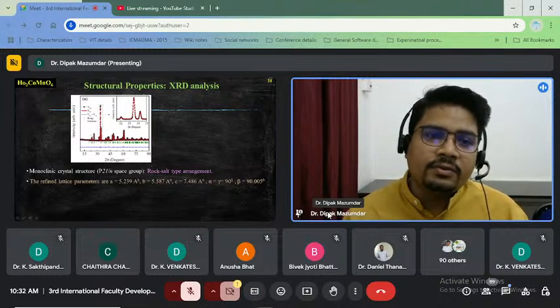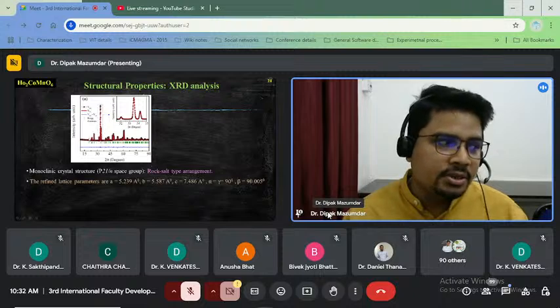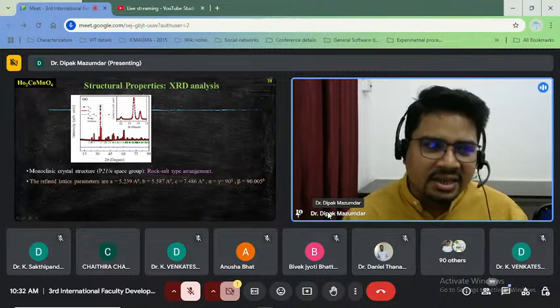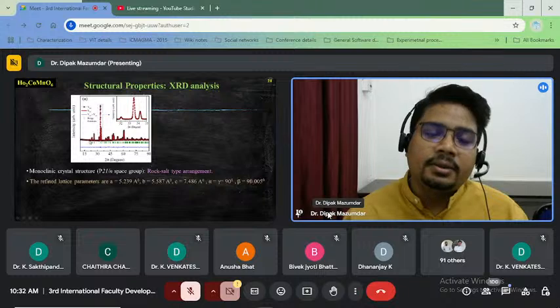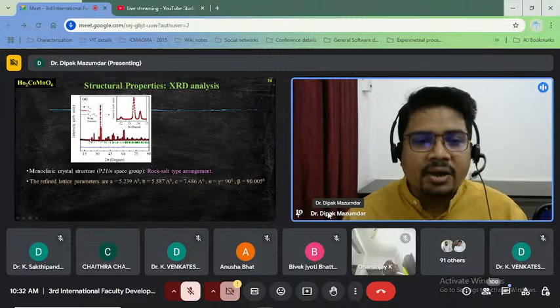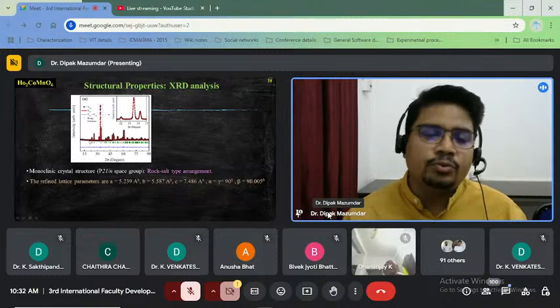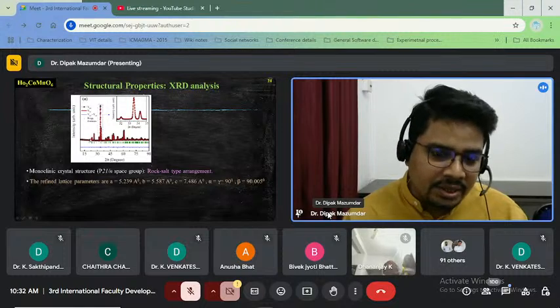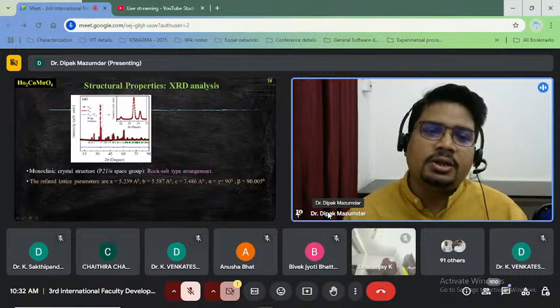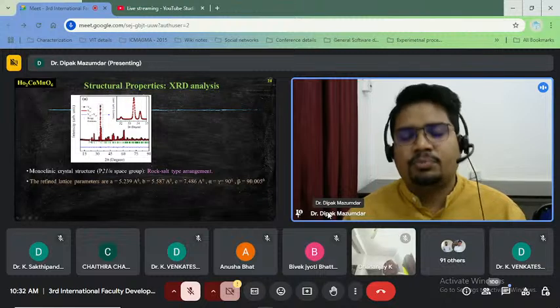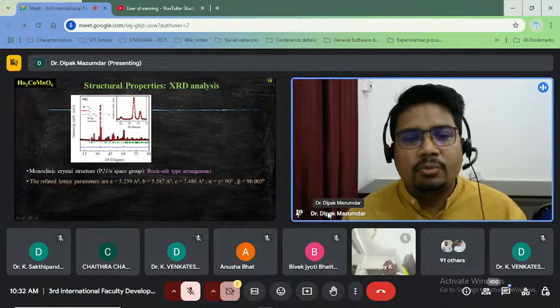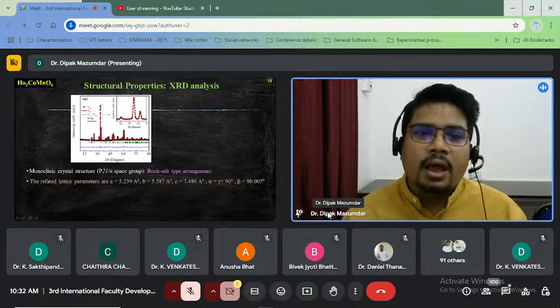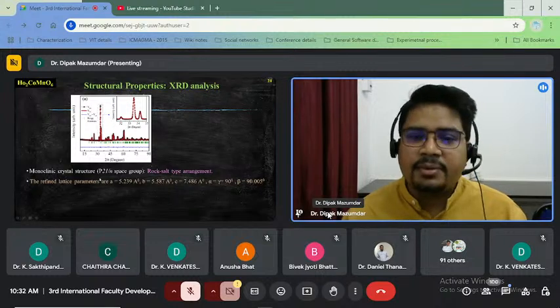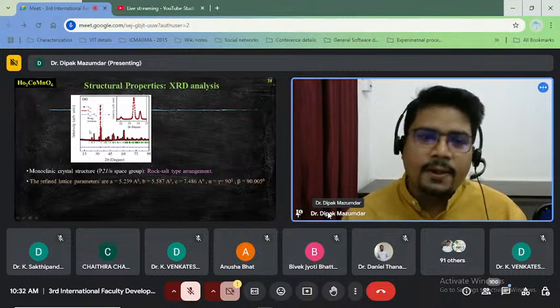Here you can observe a peak at approximately 20 degrees, and this reflects that our compound is in an ordered form. If you observe a peak near 20 degrees, it indicates that the compound has an ordered monoclinic structure. And we have refined the lattice parameters, and we get these values.